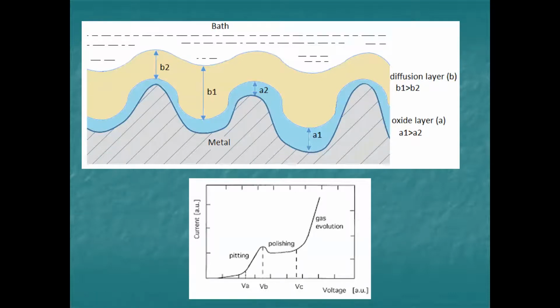If we don't have this viscous, stagnant layer, and if we do not eliminate convection in this thin layer, then the electropolishing process does not work at all. And all we're going to do is just dissolve the metal and nothing will happen. So therefore, the electrolyte is a very special electrolyte, which has to have this thick viscous layer in it, which forms on the surface. It's very thin. You can't actually see it. I haven't put the dimensions on, but it'd be some microns thick, but it won't be much more than that. It might only be a few nanometers thick.